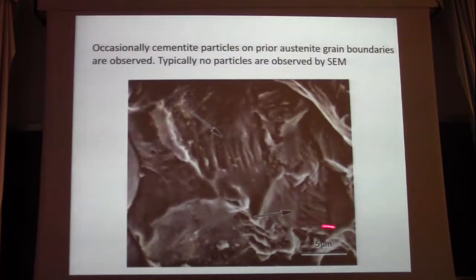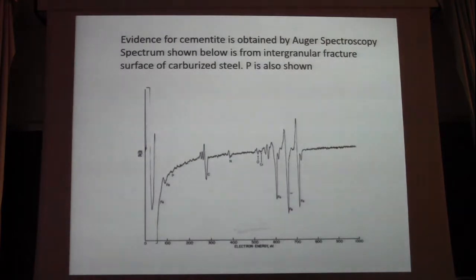Occasionally, and this is not very often, you can see some cementite that is formed. But it is cementite that produces this, and that is obtained by Auger electron spectroscopy. Low energy electrons, carbon, these are detected. And this is a relatively severe carbon peak. If you would irradiate an area within the austenite grains, away from the grain boundary, this carbon peak would be very, very much smaller. So this is evidence for cementite forming on those austenitic grain boundaries in these high carbon steels.